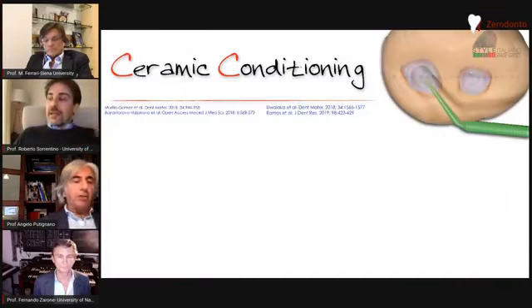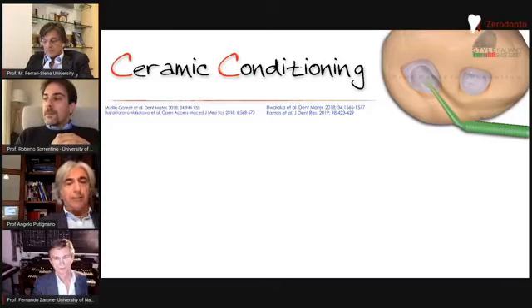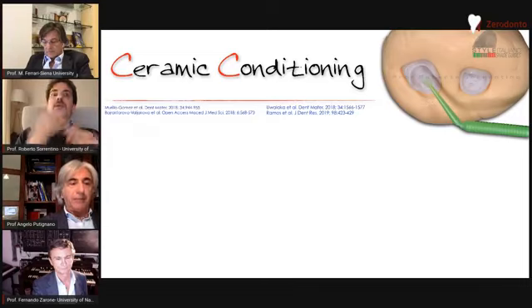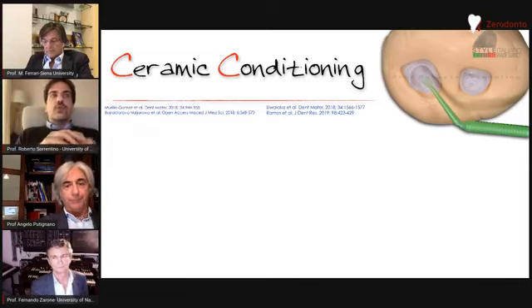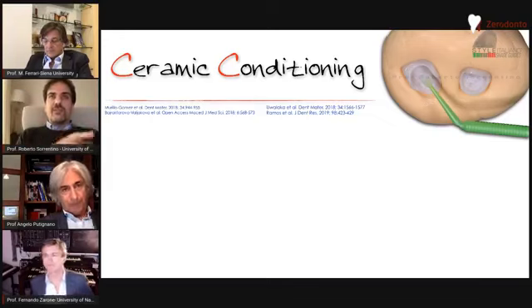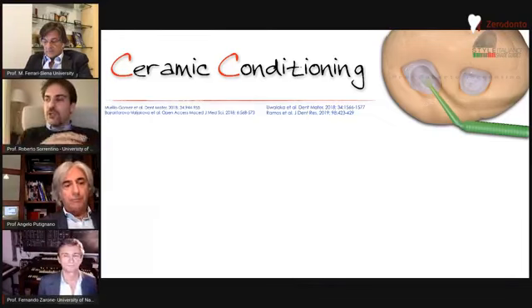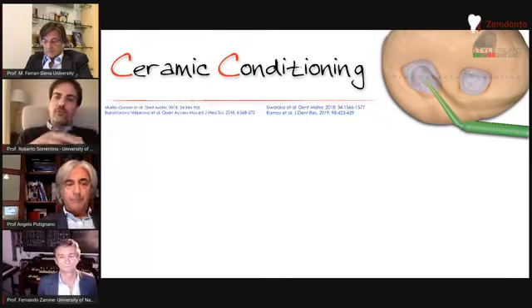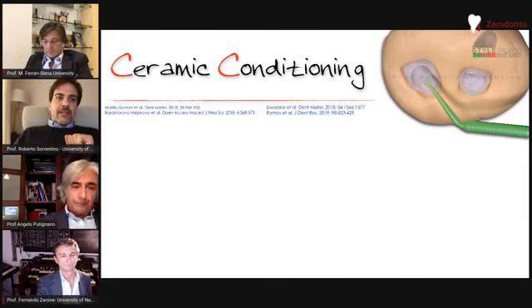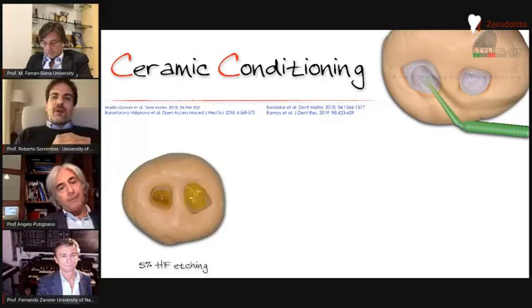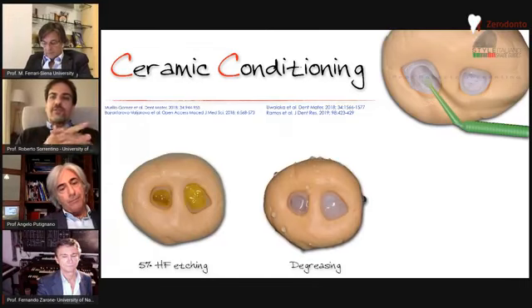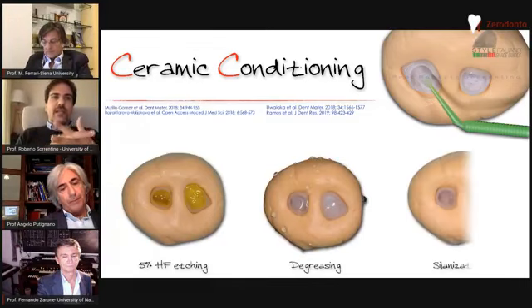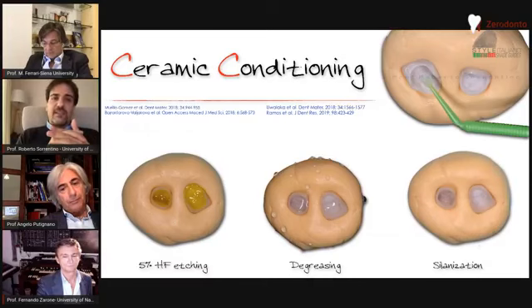There is so much evidence that yellow is the 10. No, usually it's the red that is 5, but it's the same. If you use the 10, you have to reduce the time a little bit, in my opinion. Perfect, exactly. Usually I prefer to use 5% just because of the thickness of the restoration. If you are under 1 millimeter, I prefer to use 5% hydrofluoric acid. Then you have to clean the surface by means of dedicated cleaning solutions, surfactants, or degreasing with 90%, 96% ethanol.